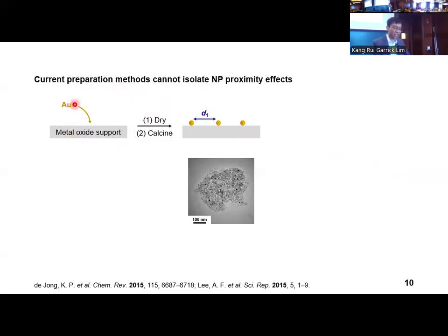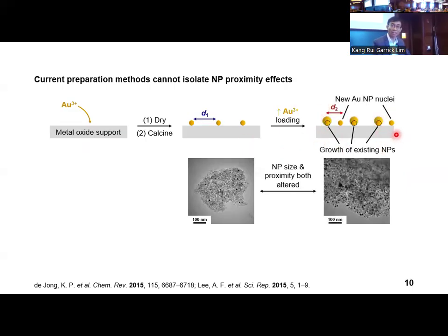A systematic investigation on the effects of nanoparticle proximity on thermocatalysis is challenging using traditional impregnation methods, where the metal precursor is introduced to the support, then nanoparticle nucleation is induced. This is because a higher metal precursor concentration nucleates more nanoparticles, thereby reducing the nanoparticle proximity from D1 to D2, but concurrently yields larger nanoparticles and thus does not decouple the isolated effects of nanoparticle proximity or the nanoparticle size on catalysis.